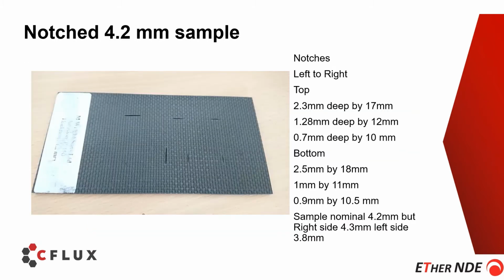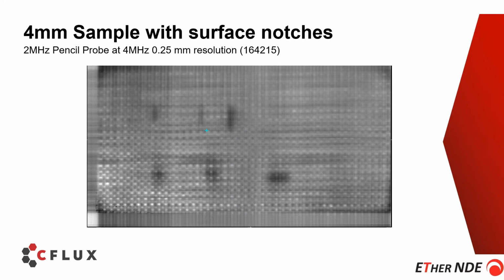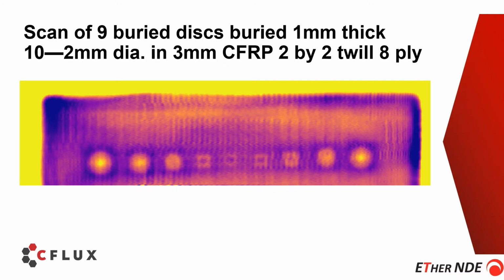We also made a notched sample with various sizes of defects in it, and this is the scan. You can also see the fabric. And more recently we looked at some centrally placed 1mm thick discs of different diameters, the smallest being 2mm by 1mm high, which is this one here.